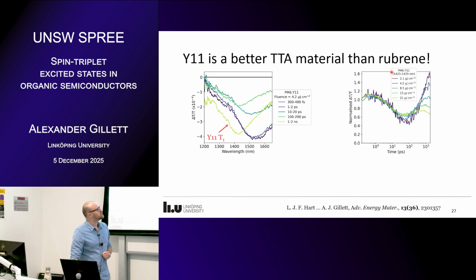Well, we get something that's quite unusual. By first glance, looks quite unusual. So dark blue is our lowest fluence, and this sort of lime greeny color is our highest fluence. So we get an overlap of the first sort of 10 picoseconds, which is just the excitons being quenched. And then what we find is, it almost looks like the lowest fluence here has the sharpest rise and the highest peak relative to this point of normalization.